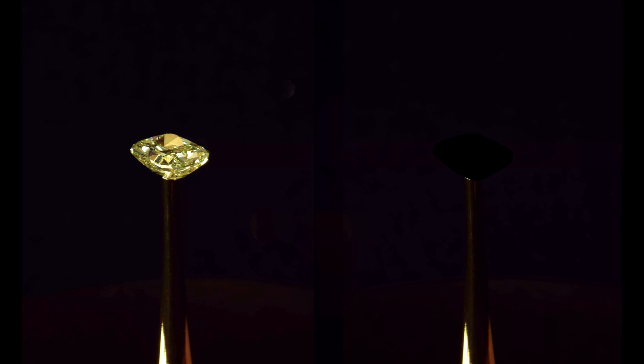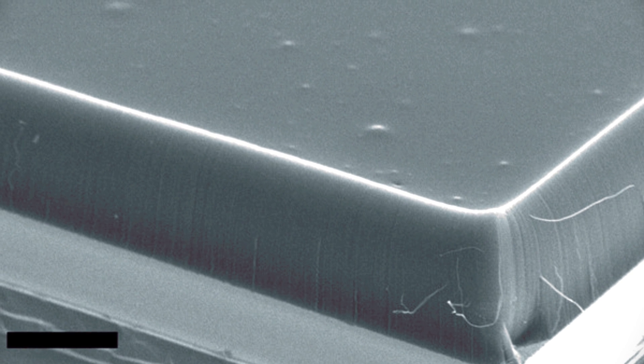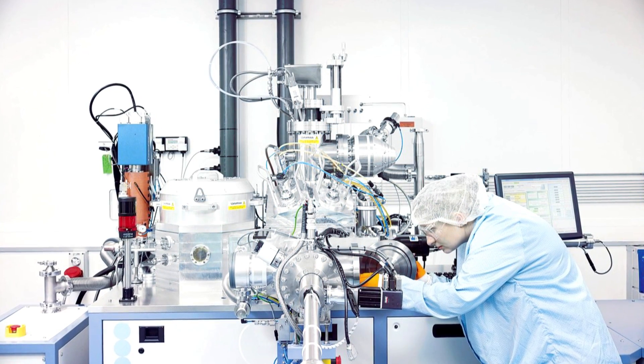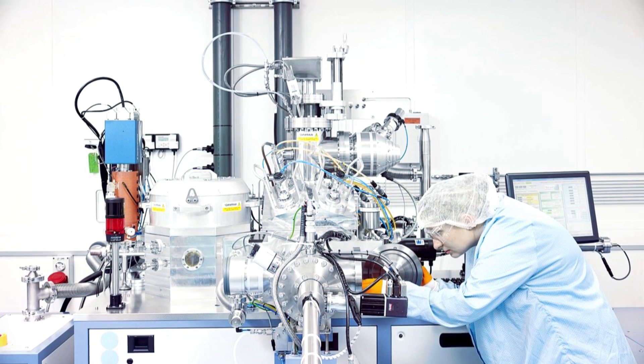In early 2019, the title of blackest material was challenged when MIT engineers announced they had created the blackest black coating from carbon nanotubes ever observed. This technique produced a material 10 times darker than Vantablack, absorbing 99.995% of visible light from all angles. Created by accident while experimenting with growing carbon nanotubes on aluminum to improve its conductivity, the coating is made from vertically aligned carbon nanotubes grown on chlorine-etched aluminum foil. Though the general mechanism of its blackness is similar to Vantablack, the mechanics of why this substrate and technique produced such a dramatic increase in absorption performance remains a mystery to the MIT team.